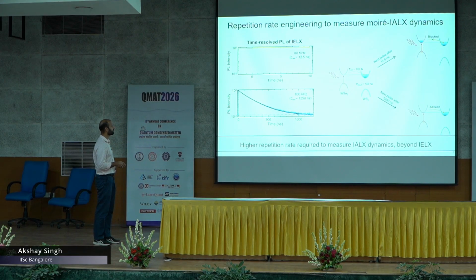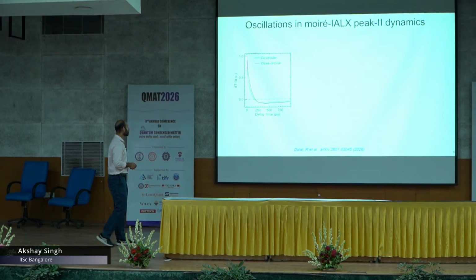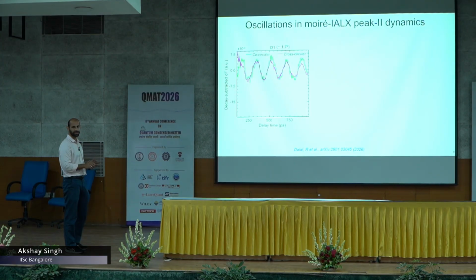So now let's go back to the oscillations that I was showing, which at least in my mind is the most exciting part of this work. What we did was we wanted to understand where these oscillations are coming from. The simplest thing we can do is change the relative circular polarization of the pump and probe. We can do co-circular or cross-circular, and what we see is that the oscillations are nearly the same. There is no circular polarization dependence.